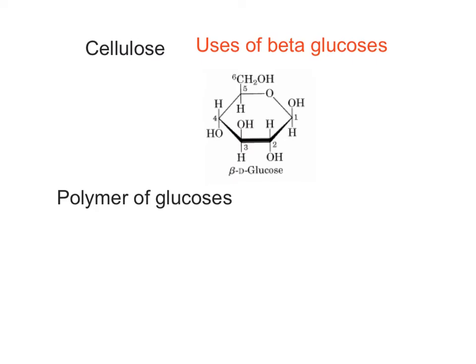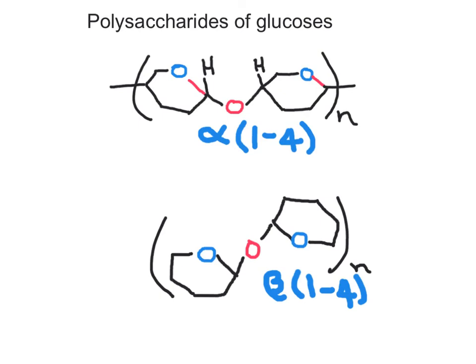The third polysaccharide found in plants is cellulose. Since it is the structural part of plants, this is the most abundant organic compound found on the planet. Different than starch, this polysaccharide uses beta-anomers of glucose. Cellulose is a linear polymer of D-glucose residues bonded by beta-1,4 glycosidic bonds. While the sugars in amylose, amylopectin, and glycogen forming alpha-1,4 glycosidic bonds have the rings in a similar fashion, in cellulose the glycosidic bonds are beta-1,4 and the ring is rotated 180 degrees, with the oxygens in very different positions than in amylose. That brings more possibilities for hydrogen bonds between these molecules.